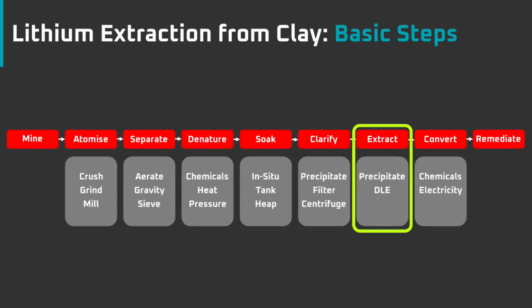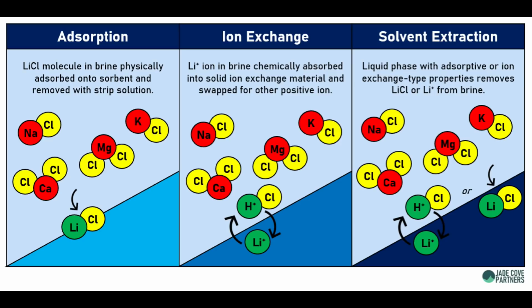There are two ways to extract the lithium from a brine where the water could be recycled. The lithium can be removed from solution with direct lithium extraction, DLE, or use chemicals that react specifically to the lithium and cause it to precipitate out of solution. DLE is a process where lithium is pulled directly from solution, and it can be done in several different ways. It hasn't been used at large scale for lithium extraction yet, but it's very close, and it appears that it will start scaling massively in the next 5 years.